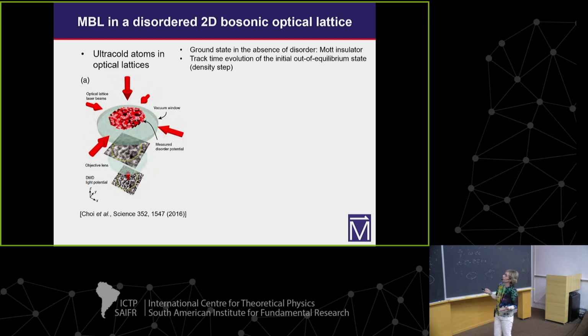In the absence of disorder, the ground state of this system is a Mott insulator. So they prepare this 2D system, and to probe the dynamics you have to take the system out of equilibrium. They do a quench experiment in which they remove half of the atoms, say all the atoms on the right side, and then measure the density imbalance with time — the difference between the number of atoms on the left and right side.